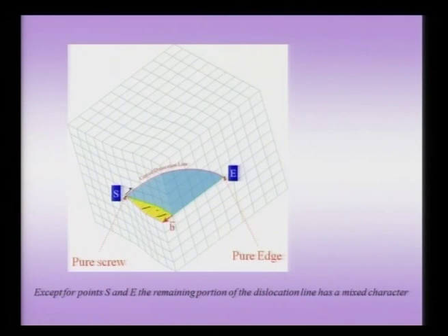But now the dislocation line, which is a curved line, comes out, and at this point the B vector is perpendicular to the T vector. Now the T vector is inward on the same slip plane, and is perpendicular to B. Therefore, this is a pure edge character here, and that can also be seen from this extra half plane which is present. So this pure edge region has this extra half plane.